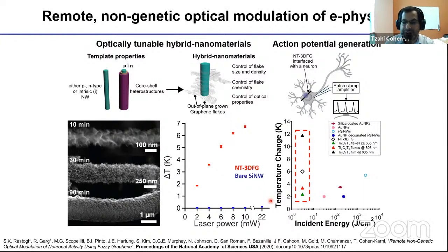If we plot the energy that is needed versus temperature rise, you can see that the materials we are using, such as NT3DFG, NT-3DFG is this one, are a lot more efficient than the rest of the materials out there, such as silica-coated gold nanorods, gold nanoparticles, silicon nanowires, and gold-decorated silicon nanowires. There are a couple more materials over here that I will show in one slide. This is just hot off the press, literally released last week. This is using MXene, which is another van der Waals flake material that we started using a bit more than a year ago.